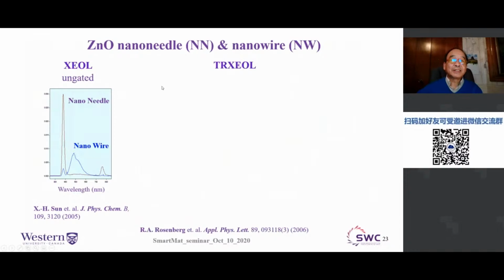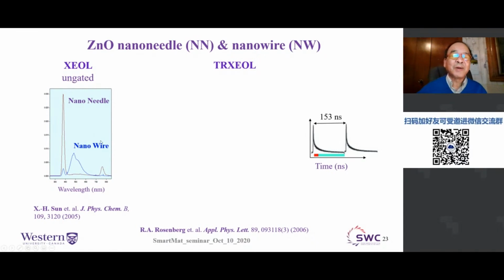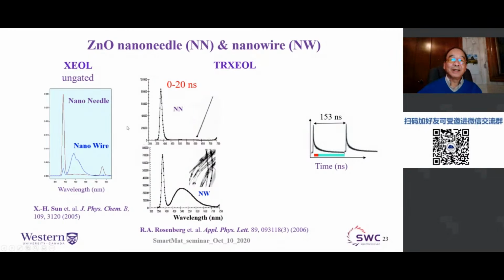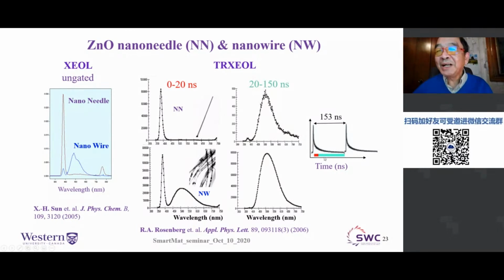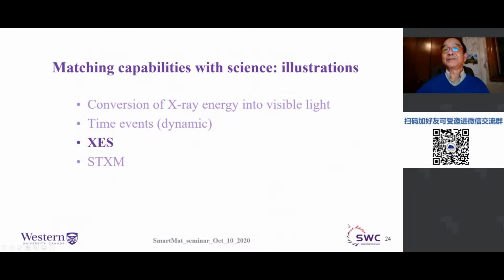I'll give you another example, right? For example, we look at two zinc oxide nanostructures. One is a nanoneedle, which is nearly a perfect crystal. One is a nanowire that has some defects. And then we do the same thing. We just select two windows, right? Say the fast window, from 0 to 20 nanoseconds. Now this is ungated. This is the low time gating. So in the crystal, obviously, the dominant is the band gap emission. And in the nanocrystal with defects, previously we don't see a lot of that. But if you concentrate on the very fast window, we see a lot more of the band gap emission. Similarly, if you look at the slow window, previously we don't see much of defect, and all of a sudden in the slow window it's mostly defect, right? So this time gating allows us to really understand the details of energy transfer into optical channels.